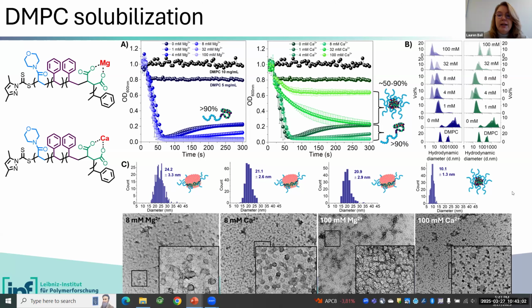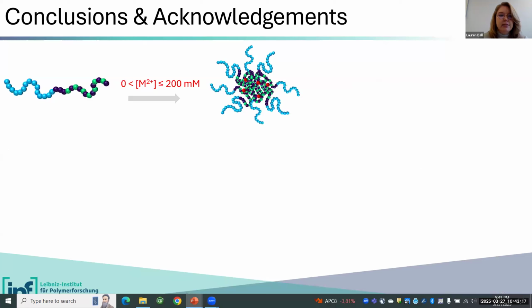And this has actually shown a really nice method to tuning the amphiphilicity of your alternating SMA in such a way that you get successful solubilization, but without the need for post-polymerization modification of your copolymer, which is very nice. So conclusions: we were able to make two different types of block copolymers, two different chemical compositions, and with very low dispersity and targeted molecular weight, which is great.